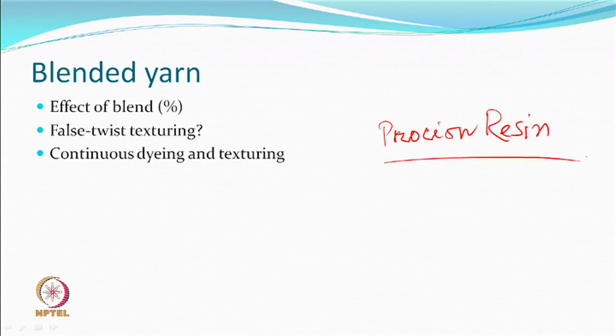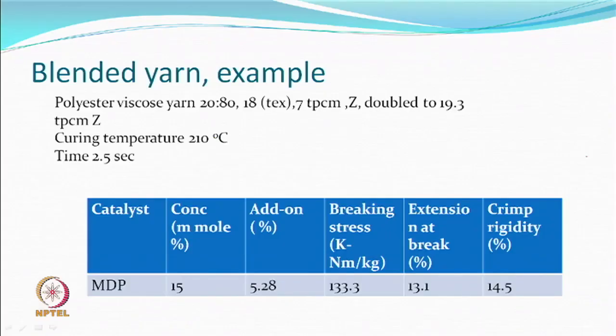Procion resin process, where in acidic medium the reactive dyes can react through the resin and dye also. So one can think of, you go for a high temperature curing, you can go for a mixture of dye and resin, and theoretically you can do continuous dyeing and texturing. So one example here is where less polyester has been taken, more viscose. But if you change the percentage of polyester, obviously thermomechanical setting of the polyester will help. If it is more of viscose, you have to have more of cross-linking agent. So similarly done, 210 time 2.5, same catalyst, it's a blend. So you can do texturing as well.